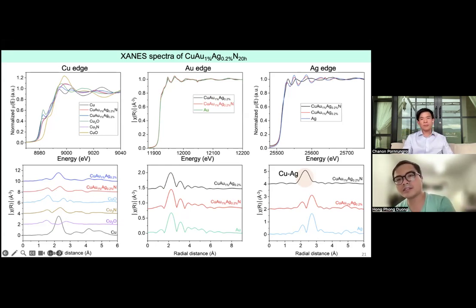But on the other hand, for silver it was very interesting. We found a shift in the nitride sample, as you see here. The sample without nitridation had silver that looked like only silver bonding. But with the nitridation, we see that copper and silver were actually bonded together. It makes a copper-silver bond, which also explains why the silver was kind of isolated atoms, and on the other hand, gold was like nanoparticles. So this result was confirmed by both EXAFS and EDX and TEM.